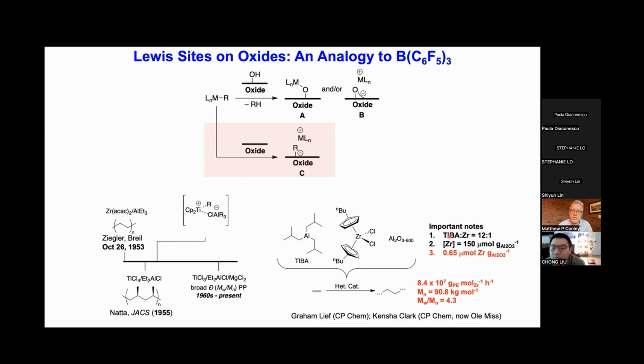And there's some important notes here. First is that the TIBA to zirconium ratio is about 12:1. There's a good amount of zirconium in the feed, but barely any zirconium adsorbs to the support. So we knew that we were kind of in for a difficult problem.